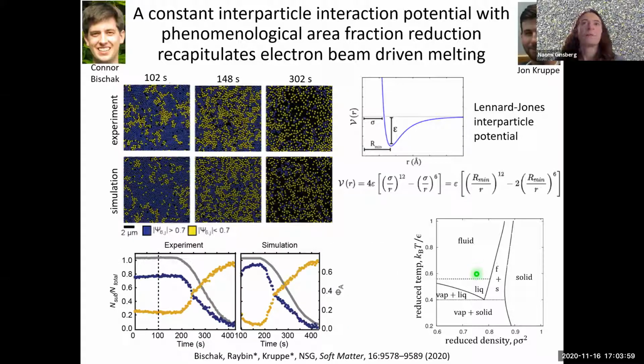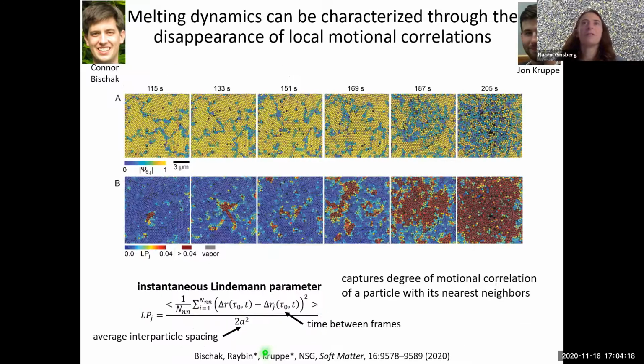Okay, so it helps, however, to be a little bit more quantitative than that. So I'll show you 2 of the parameters that we use to do that. First, here's good agreement in the evolution of the ordered in blue and disordered in yellow fractions of the system. Okay, so that's good. But to be even more precise in terms of characterizing the melting, we can employ a so-called Lindemann criterion. So traditionally, the so-called Lindemann parameter diverges when melting occurs.